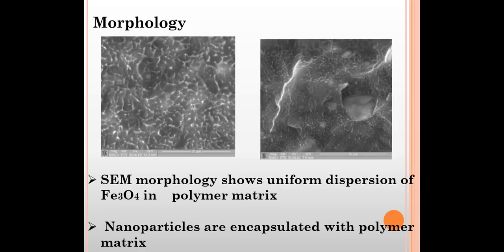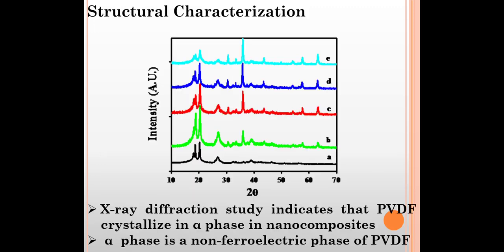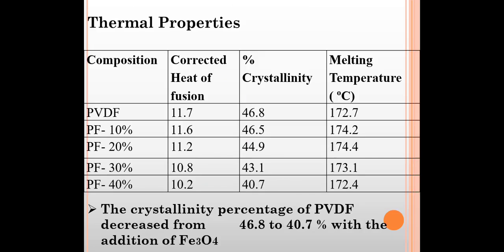The polymer nanocomposite morphology is studied using the SEM technique. The SEM morphology shows that nanoparticles are uniformly distributed in the polymer matrix. It also shows that the nanoparticles are encapsulated by the polymer. The structural characterization indicates that the polymer PVDF crystallizes into alpha phase and no other extra peaks appear with the addition of Fe3O4 nanoparticles. We have studied the thermal properties using differential scanning calorimetry.